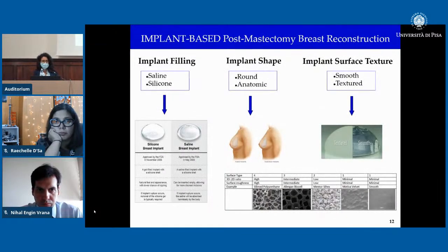And the currently used implants can be divided depending on their shape and their surface texture or filling, because they're all made of a shell that gives strength and a filler that gives bulk and consistency. And concerning the shell, the surface texture of the shell can be smooth or textured. Smooth implants have the drawback that they move within the breast implant pocket, while texturization increases the stability of the device, but is associated with an important complication that we will see later. While concerning the filling, it can be saline or silicone, but saline prostheses have a consistency that is like that of water, and they tend to wrinkle under the skin, while silicone breast implants more accurately mimic the breast feel, and so they are by far the most commonly used.